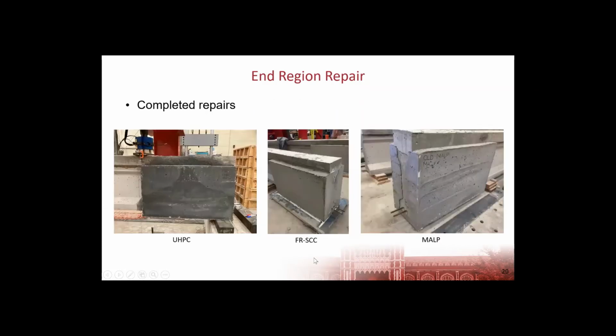So this shows some of the specimens after the repair. The UHPC on the left and the FR-SCC in the middle both had a very smooth finish. We cast both of those specimens by pouring material into the forms from one side, letting it flow underneath the beam, and fill the other side until we completely filled one side, and then we would shift to the other side and top off the repair.